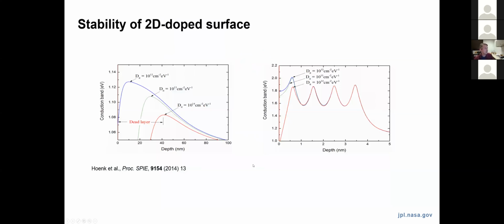Another way of illustrating the effectiveness of this delta doping process is in the calculations that I'm showing here. These were done by Michael Hoenk, showing a calculated conduction band profile for a theoretical device that has ion implant backside passivation. So there are other techniques you could consider to introduce charge at the backside of the device to counteract this dead layer. Ion implantation, even in the best case, has a length scale on the order of tens of nanometers. So although you can improve the potential well characteristics, you're still susceptible to changes in the interface state density. So that's this Dit number. So variations in the trap density at the back surface of this ion implanted device still modulate the depth of this dead layer and lead to some of the instability issues that I showed a few slides ago.